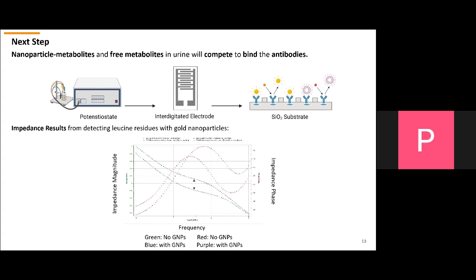And here with this graph, we can focus on the impedance magnitude curves, which are the blue and green curves, where green represents no gold nanoparticles bound and blue represents gold nanoparticles bound to the electrode. And as you follow along these curves, they begin to form a gap. And where this gap is largest is where we can determine the best frequency to measure this impedance change.